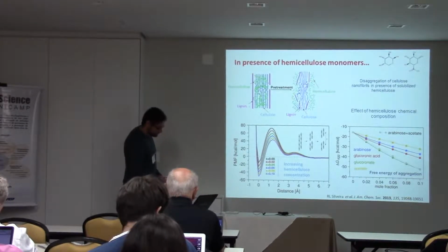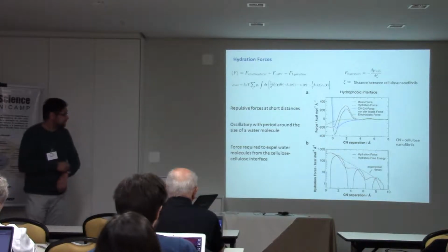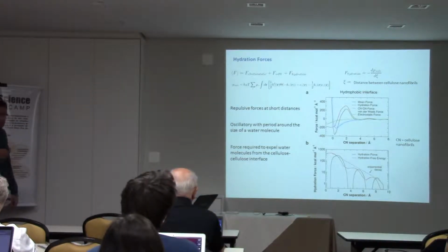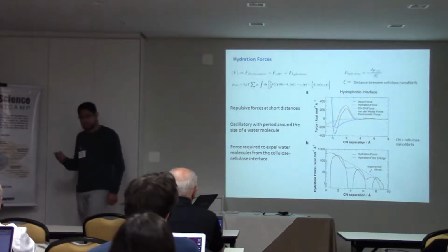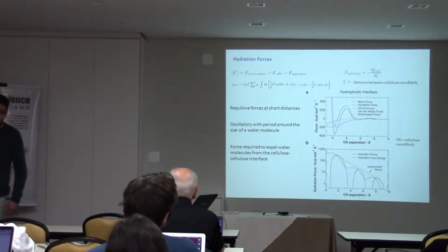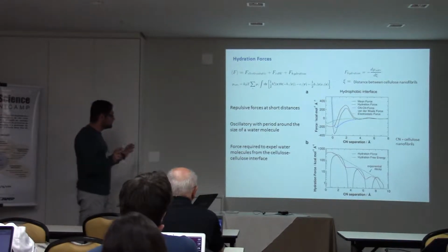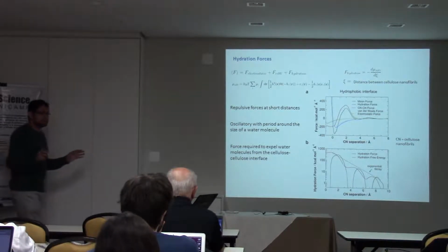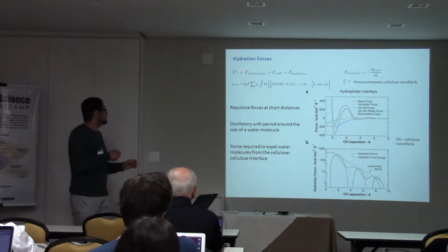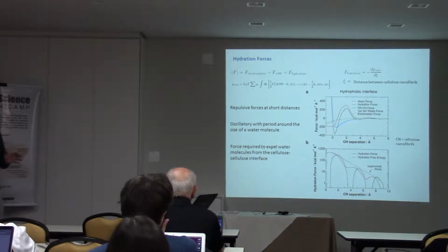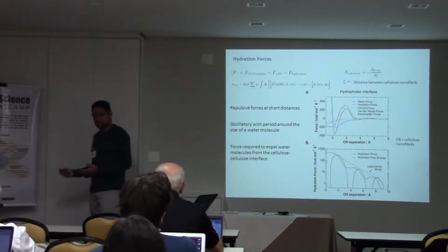And from this theory, we can also, instead of analyzing the PMF, the free energy profile, compute forces. And this is not mechanical forces only. For example, let's imagine we have two cellulose fibers, and these cellulose fibers will interact through electrostatic interaction. So you have an electrostatic component, you have a van der Waals component, and you have another component that's not mechanical. This is thermodynamic.